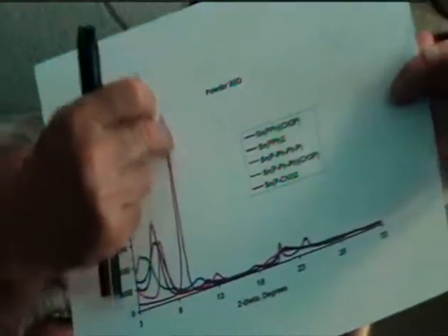And unfortunately, I forgot the X-ray patterns, we're never going to get a structure. Here's the just the methyl phosphonic acid with a few peaks, and here are the mixed derivatives and the phenyl. So this gives us the interlayer spacing. It looks exactly like there's zirconium, the X-ray patterns look exactly like zirconium phenylphosphonate. And now they're telling me they're nanoparticles, so what is going on here?